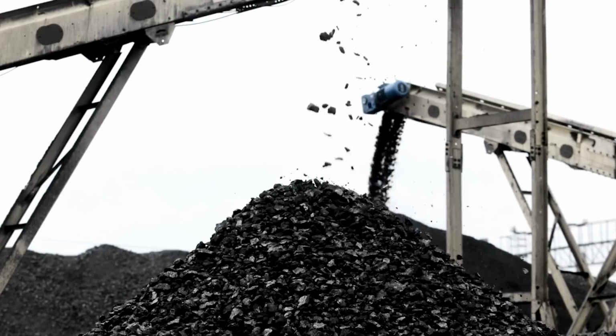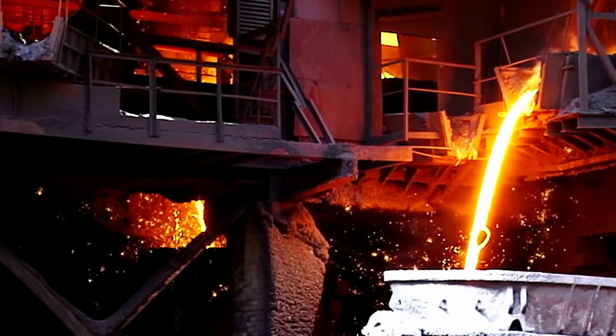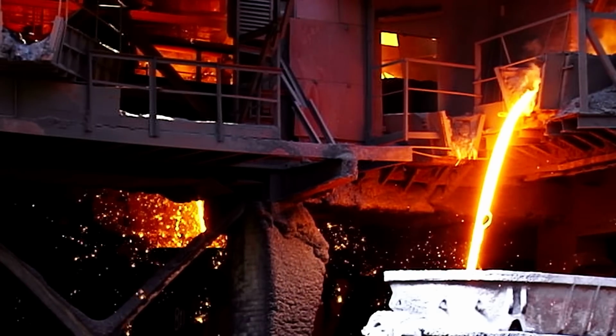It's usually cheaper to produce less clinker, so the use of supplementary cementitious materials is already widespread in the cement industry. One problem with this is that the road to net zero in other industries is likely to limit our access to many of those materials. Fly ash is a byproduct of coal, and blast furnace slag is a byproduct of blast furnaces in steelmaking. As coal usage goes down and the steel industry moves away from blast furnaces, availability of those materials is going to dwindle, meaning that there are going to be some limitations on this method going forward.